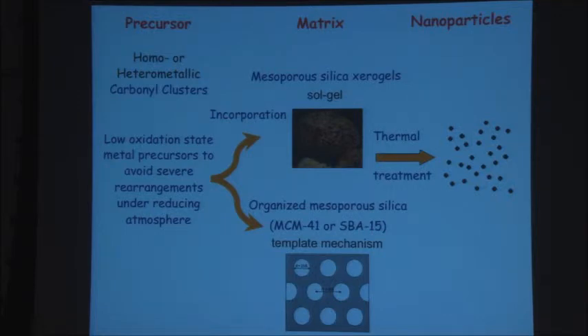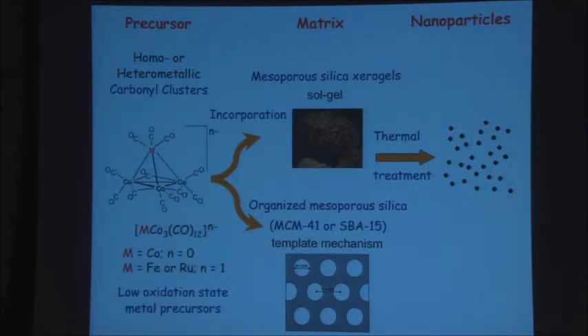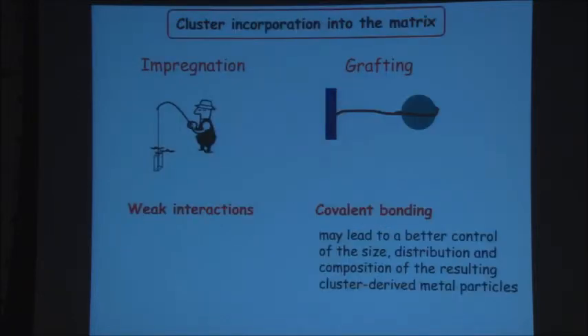So we want to have low oxidation state clusters. So one of the candidates we took was this tetrahedral iron or ruthenium cobalt-3 cluster, only carbonyl ligands, which can be easily removed thermally. And these metals were chosen because the physicists we were collaborating with were interested in magnetic properties of cobalt nanoparticles in the presence or not of a second metal, like, for example, iron or ruthenium. So these were the candidates we selected.